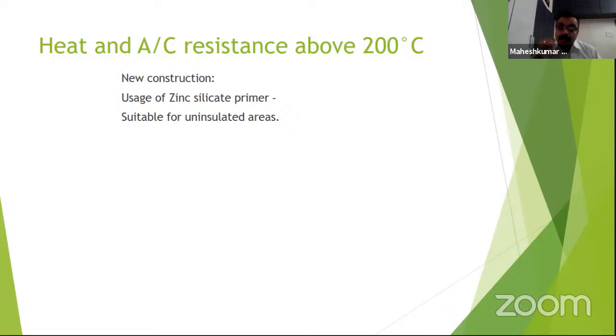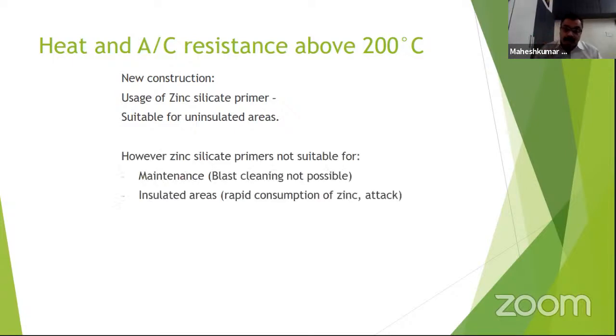It may be a very high concentration of electrolyte near the voids, which may completely destroy the coating if the temperature is high and the line is getting colder, because of the condensation that happens onto the surface while it is getting colder. So when this happens, we go with the issue like corrosion under insulation.